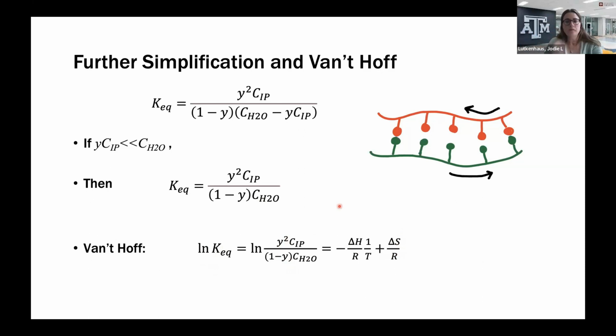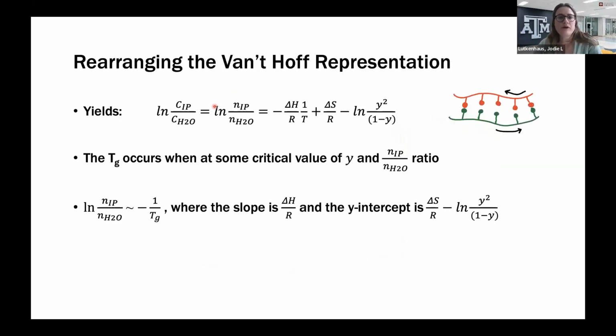Okay. So by bringing that in, we can now say the natural log of our intrinsic ion pair to water ratio, by concentration or by number, because they're all in the same volume, will scale with 1/T. And if Y here is that critical fraction required to undergo the Tg, then this T becomes Tg. The slope would have that enthalpy, and then the y-intercept would include an entropic term and then another term that relates the critical fraction of polyelectrolyte, or critical fraction of a weakened polyelectrolyte, to go through the glass transition.